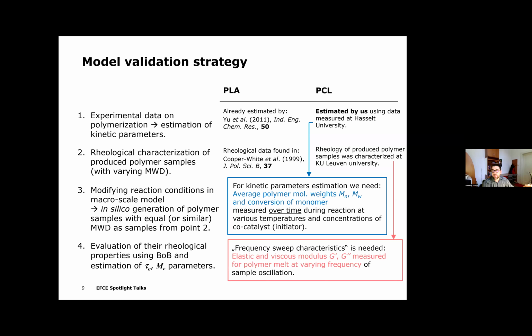And for the rheology, they sent these samples a few kilometers away to the city of Leuven, where our colleagues from different research groups measured the rheology, and we have just this very fresh data. The rheology measurement is usually called frequency sweep characteristics, which means a dependency of elastic and viscous modulus G' and G'' on the changing frequency of the oscillation of the sample during the rheological measurement.